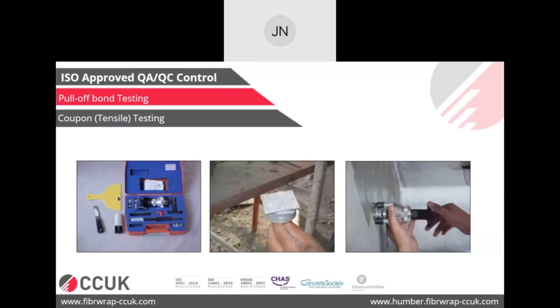So in this particular pull-off test, this is slightly different from the concrete pull-off test we do. In concrete, we get a pull-out strength, which tells us how strong the concrete is. In this case, basically, we're just testing the bond between FRP and concrete. So all we want to see is that when you pull it off, it should not come out from the substrate only, or it should not come out from another layer of FRP if there are multiple layers. So in this case, you could see when we pulled it off from the side of this beam, it took out some concrete with it, which shows that in future, if anything fails, that will be the concrete due to crushing and not the bond between FRP and concrete. That's the pass criteria for this test.